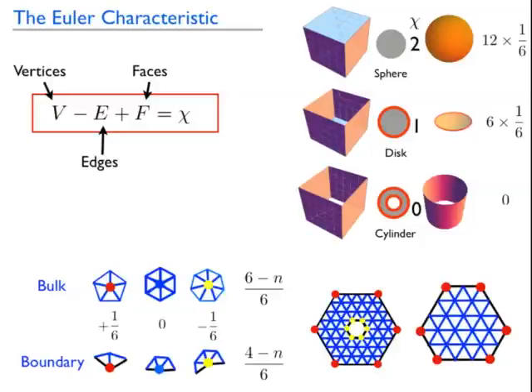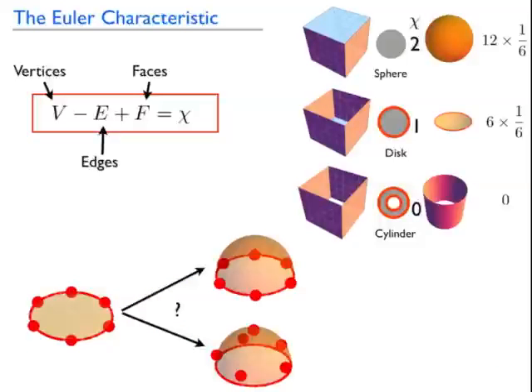And now the question is, if I make something like a dome, I now have to worry whether, up to now there's no question. If I have a sphere, I have 12 fives. If I have a disk, I have 6 threes on the edges. But now if I have something like a dome, which both has a surface and an edge, where do they go? And that's no longer a question that's strictly given by topology. Topology tells me the sum has to be 6, but it doesn't tell me where they have to be. They could be on the surface, they can be on the edge. That depends on energy.